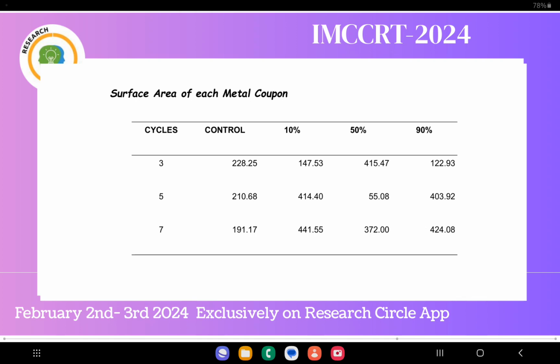In contrast, the 50% and 90% exposure levels demonstrate more erratic patterns, with values oscillating between significant increases and decreases across the cycles. This variability in surface area data underscores the complex interplay of corrosion processes, with differing impacts at distinct exposure levels and cycles. Further analysis and experimentation are essential to understand the underlying mechanisms influencing these surface area variations.